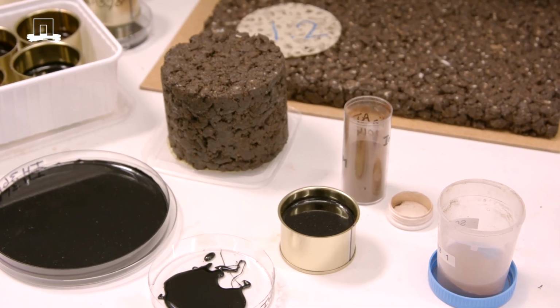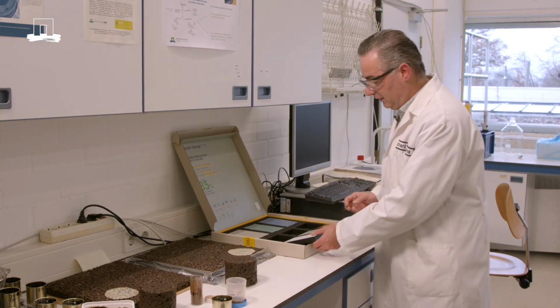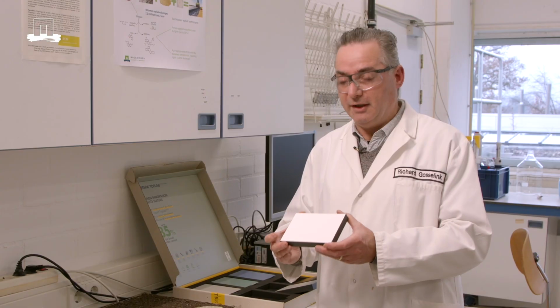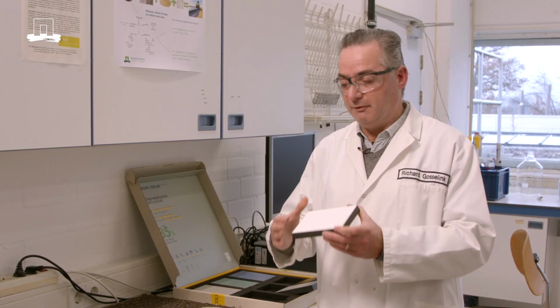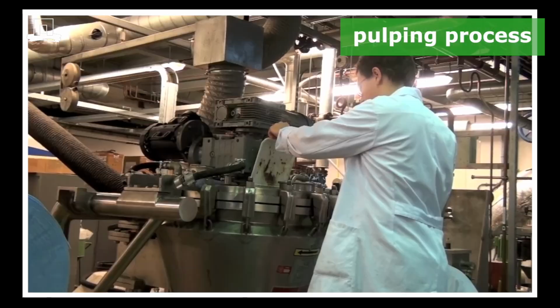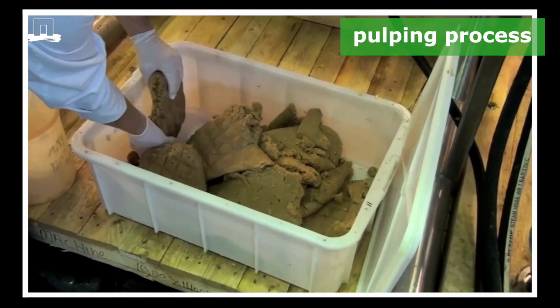Additionally, we also use this lignin in a phenol formaldehyde resin in these panels, and these panels are high performance panels for tabletops and for furniture, and this binder can be replaced by 50% of lignin with the same quality, with the same performance, and we are now also developing a 100% alternative to this binder to get a more sustainable product in the near future.